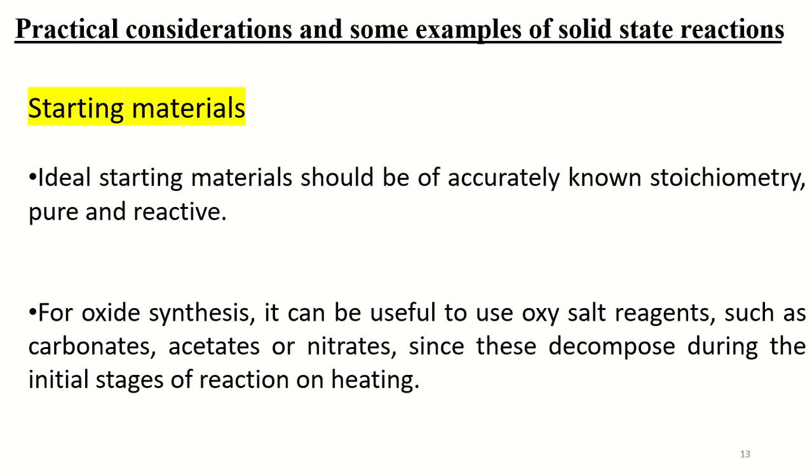Other problems may arise, however, such as potential loss of reactants by evaporation, for example alkali metal oxides, lead oxide, bismuth oxide, and mercury oxide, or sometimes reactivity towards the container, for example with transition metal containing materials.